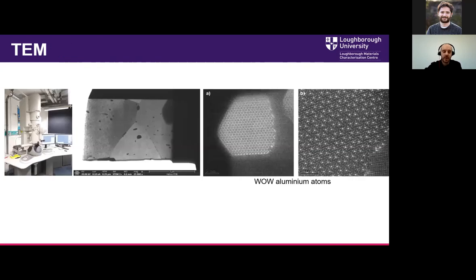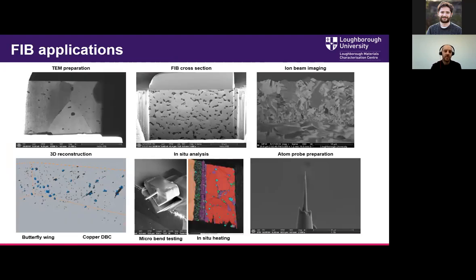So what would that look like? If we polished a sample down like an aluminium sample, we'd polish it so it was, well, not atomically thin, it's like a 60 nanometers thickness, and then we could do some high resolution imaging on it, for instance, and see all the way down to the atomic level. So what are the applications of FIB?